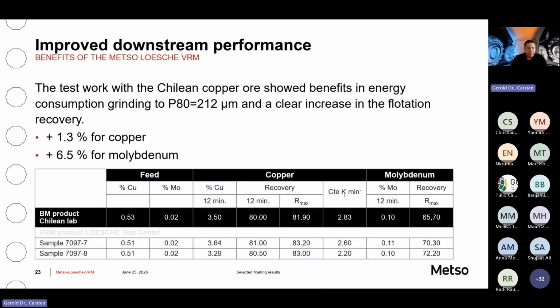Here's an example of a Chilean copper ore that we ground to a P80 of 212 micron. And as it's a dry grinding technology, you can easily imagine the galvanic interactions that you face when you have wet grinding, with all the high grinding media consumption in the ball mill, are having a strong effect on your flotation performance.